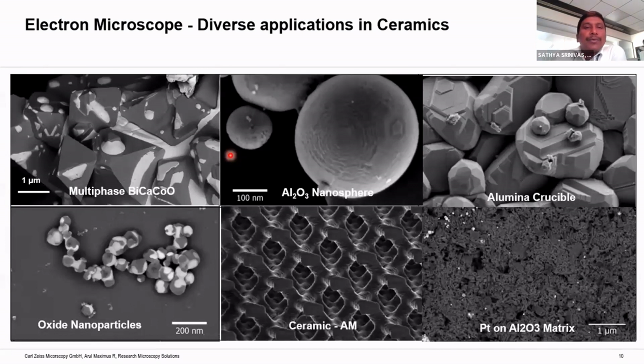A few more examples in ceramics, where these are completely non-conducting samples, but the charging effect, the contrast imaging, all these things. If you see this nanometer scale, the scale I'm talking about is 100 nanometers. So at 100 nanometers, almost more than 1 lakh or 1.5 lakh magnification, the surface features, the facets of this alumina nanosphere, you can very clearly see, right? So that is the strength of the field emission source. Because these are all non-conducting samples.